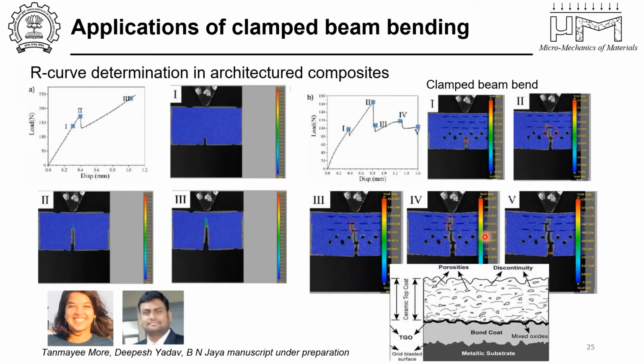The other thing we are currently pursuing is to make architectured composites and evaluate their fracture toughness using these kinds of geometries. So this is again PMMA, and this is PMMA with these structures that have been laser cut from it. These are just holes and dots and dashes sort of a thing. The dots and dashes are basically coming from the features that you would see in a plasma spray coating, the kind of pores that you would see, the intersplat pores and the gas porosities. So we got inspired from this sort of microstructure and put it into an architecture.